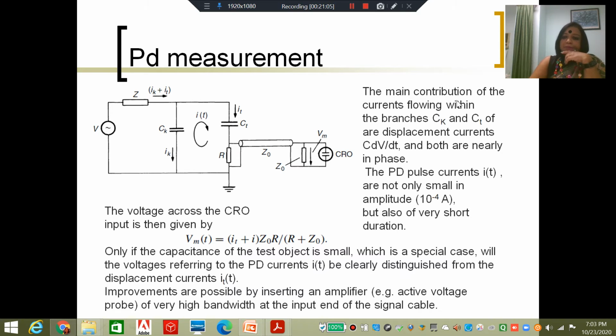The main contribution of the currents flowing within the branches CK and CT are the displacement currents C dV/dt, and both are nearly in phase. You have the branch CK, the coupling capacitance, and the branch CT, the test specimen, and both of them will see displacement current flowing through them, and these two displacement currents will be almost in phase. Now, the PD pulse current IT is not only very small in amplitude, but also of very short duration. Typically, they're of the nanosecond range in duration, and the amplitude is like 10 to the power minus 4 amperes. So that is the current that would be flowing in the test circuit.